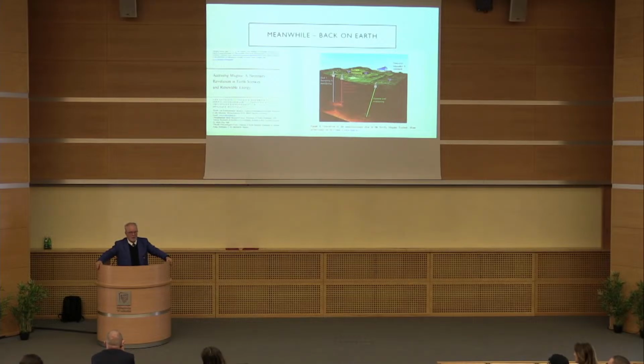My answer to that, and I'll be interested to hear your reaction, is that what we're really interested in is the length scale of the material mechanism of failure. The length scale of the material mechanism of failure for us is the bubble spacing in the magma which we're about to destroy. Remember I said that the process is very slow compared to the acoustic velocities. Why is it so slow? Why doesn't it simply go with the acoustic velocity? We infer that it is a crack propagation mechanism between adjacent bubbles which is causing the failure. So if we can have the same scale of that bubble spacing in the same material, at the same temperature and the same pressure, I would argue that we are scaled to the effective length which is important for at least the material transition into fragmentation.